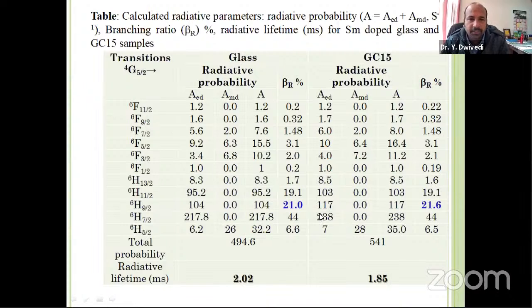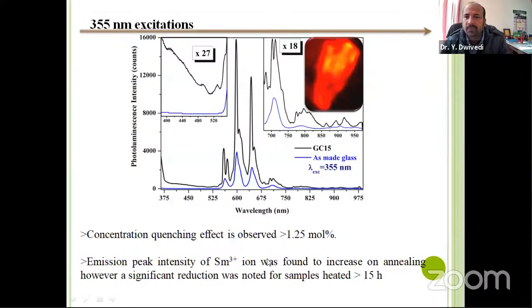On the basis of this radiative probability, we have estimated the lifetime, and in case of glass ceramic the lifetime reduces to 1.85 in comparison to glass, which is 2.02 milliseconds. So the lifetime actually reduces, which shows that the transition probability is more.